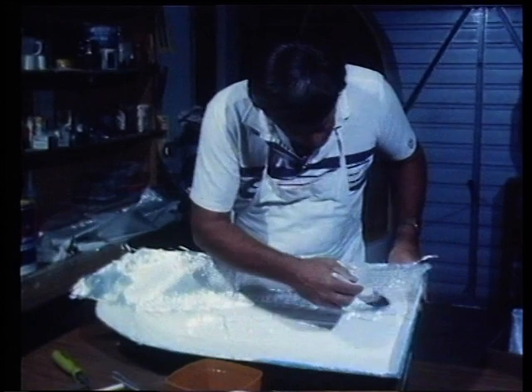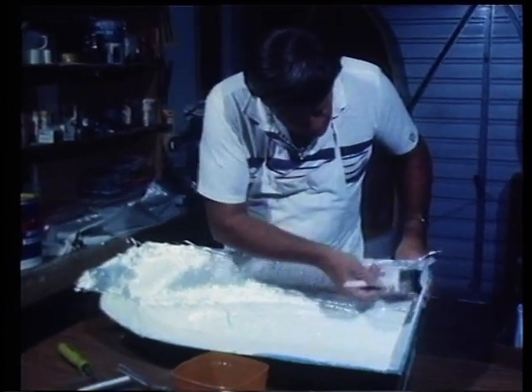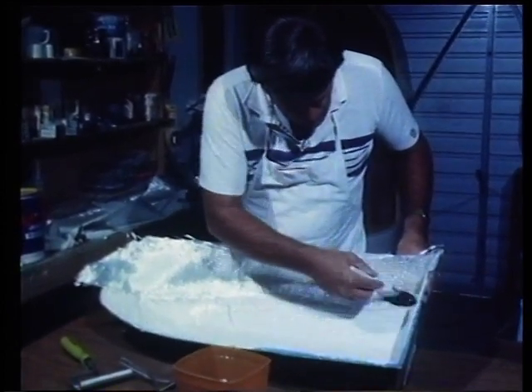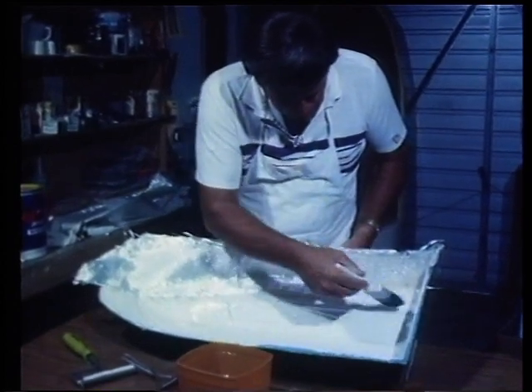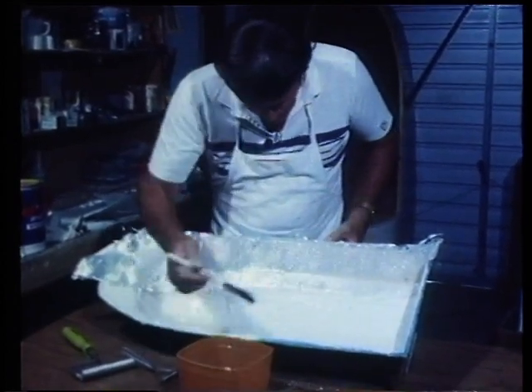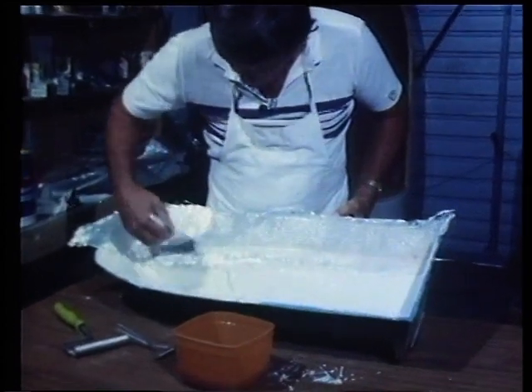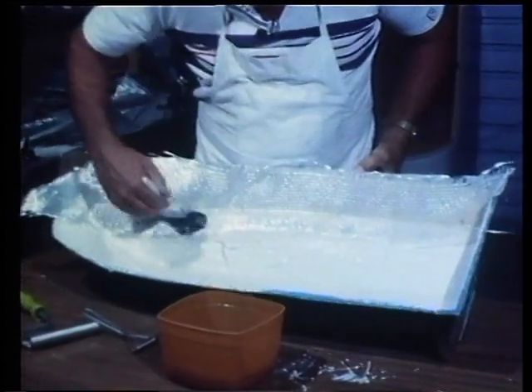You then very carefully wet it out without using anywhere near as much resin as you used for that first layer of chopped strand mat, because remember, there is a fair amount of resin in that mat which will be worked up through the woven roving as you roll it.